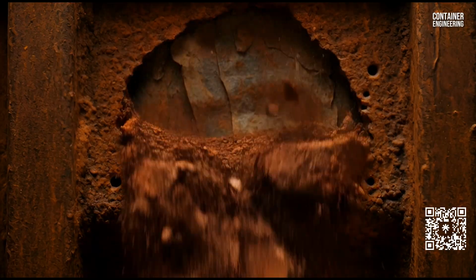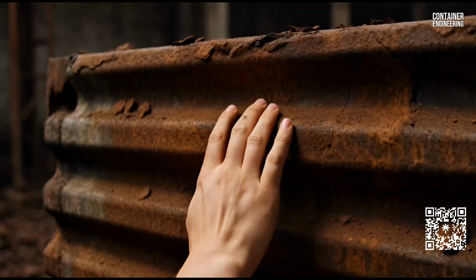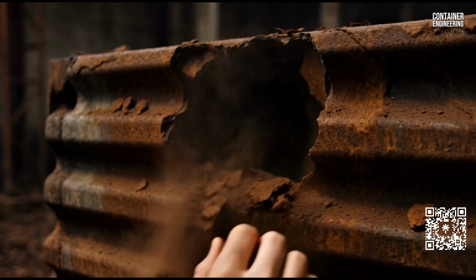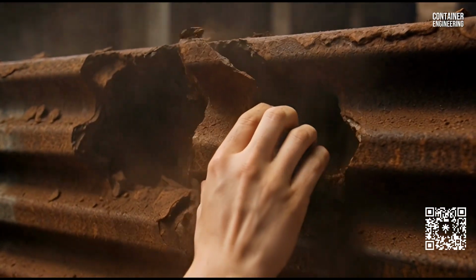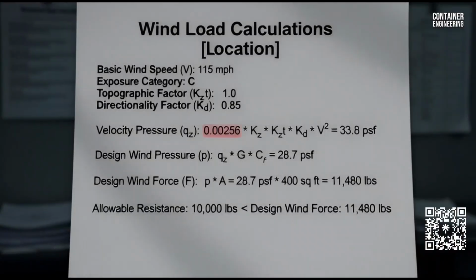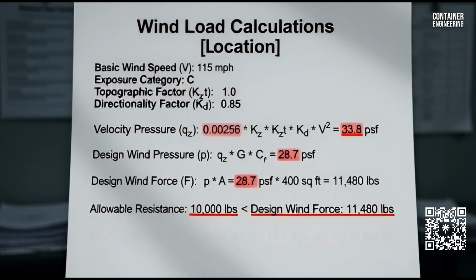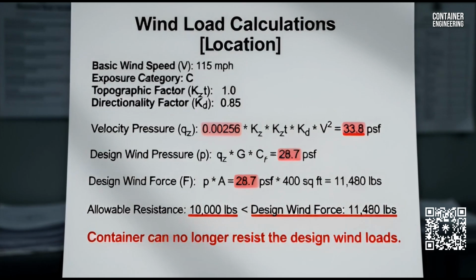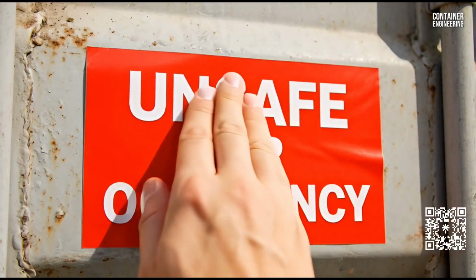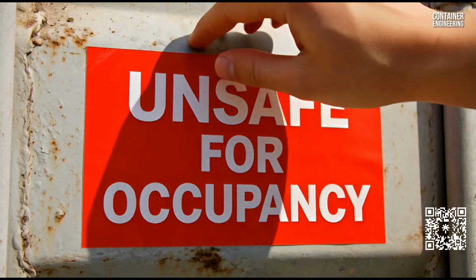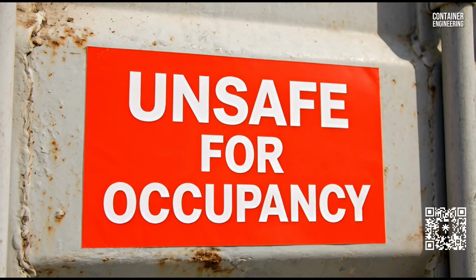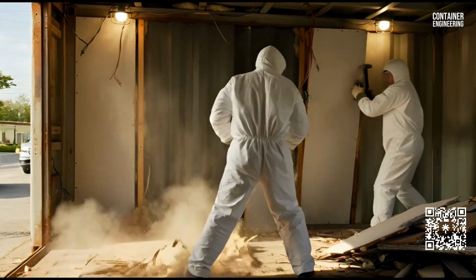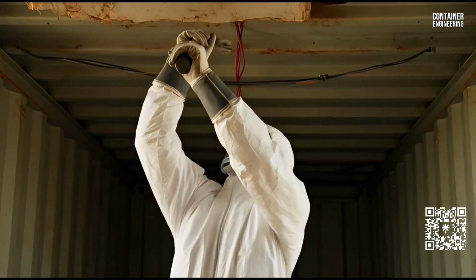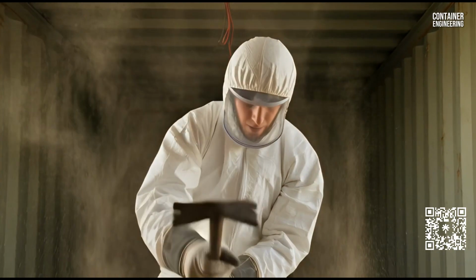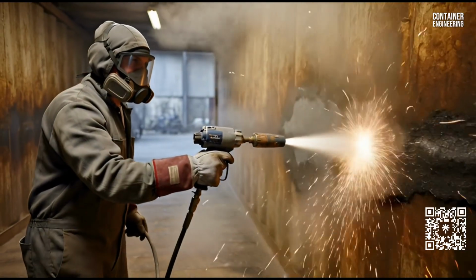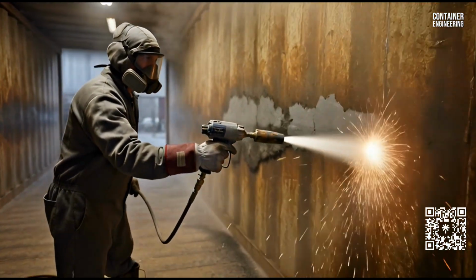Fourth, inspect annually. Remove access panels and check for rust. Use an ultrasonic thickness gauge to monitor steel thickness. If you detect active corrosion, address it immediately. Corrosion is progressive, it accelerates over time. The specification that matters. In coastal environments or high humidity climates, your coating system should be designed for a minimum 15-year service life in immersion conditions. That's a higher standard than typical architectural coatings, but container homes trap moisture, so you need industrial-grade protection.